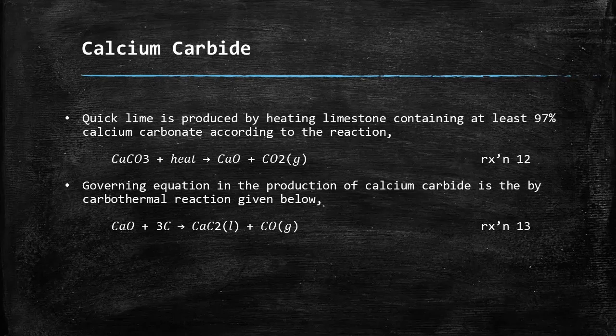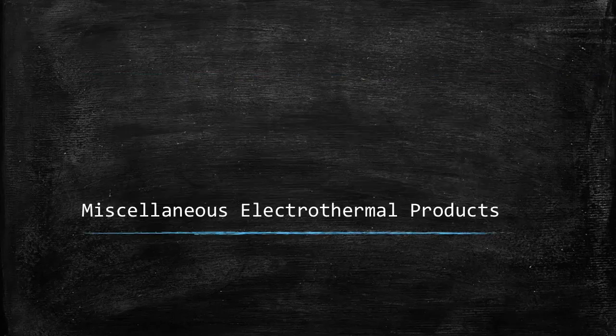Governing equation in the production of calcium carbide is the carbothermal reaction given below. The reaction is highly endothermic, having a standard heat of reaction of positive 110.484 kilocalorie per mole. With this great heat requirement, electric arc furnace is usually used. Process flow in the production of calcium carbide is the same as that of boron carbide. High-grade materials are mixed, reacted in the furnace at 2000 to 2200 degrees Celsius, cooled, crushed, packed, stored and distributed to the target clientele.